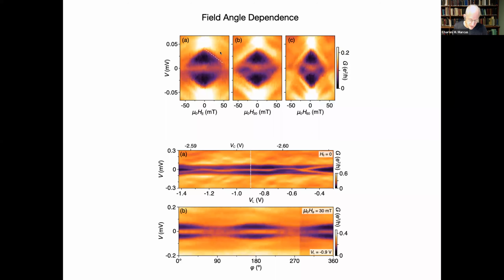And we think we understand why, but let me just say phenomenologically, and also that the slope of this line constitutes a rather large G factor. That's probably not what's going on. Probably what's going on is that the europium sulfide is being magnetized fully by the external magnetic field, and that's what's driving the gap of the superconductor to zero. So the gap is already pretty small. The gap is 4 times smaller than the gap of just the aluminum, or the situation where they're on opposite interfaces. Here we can move the magnetic field around.